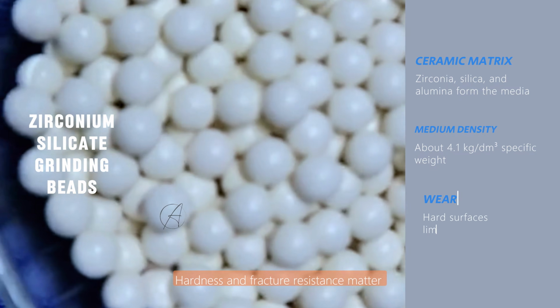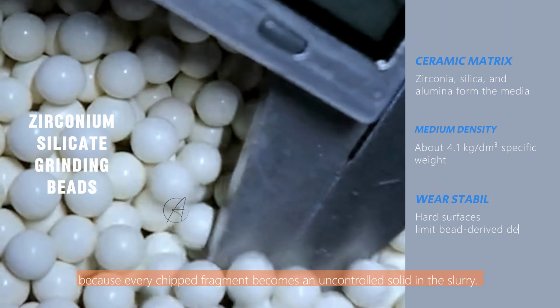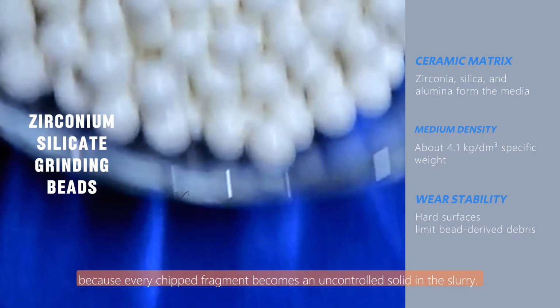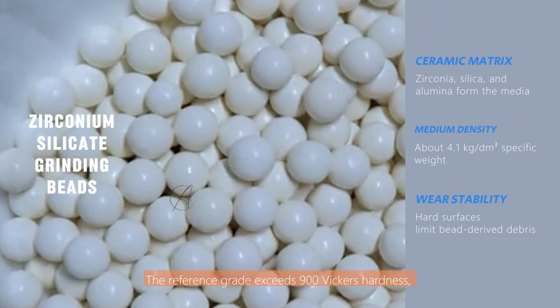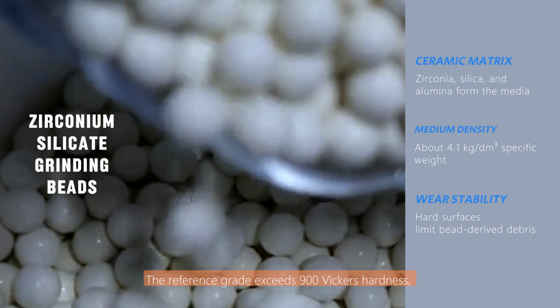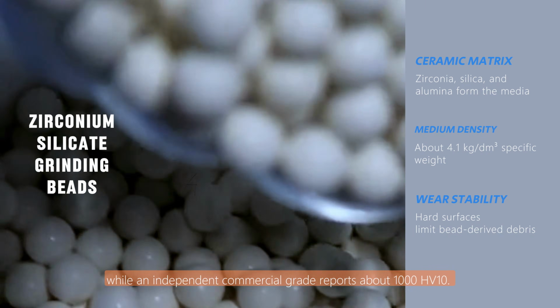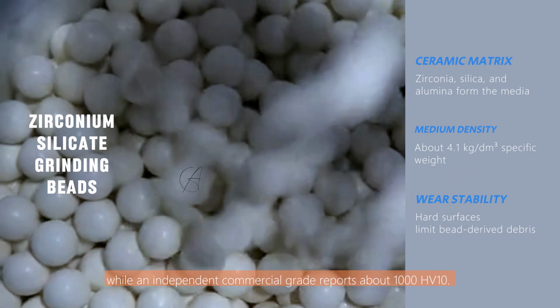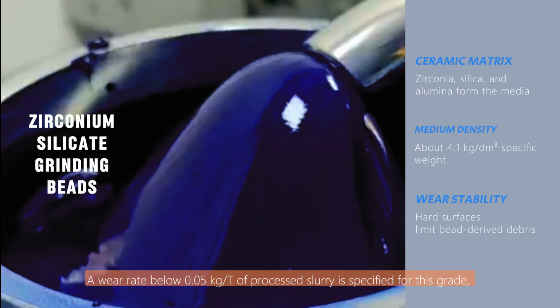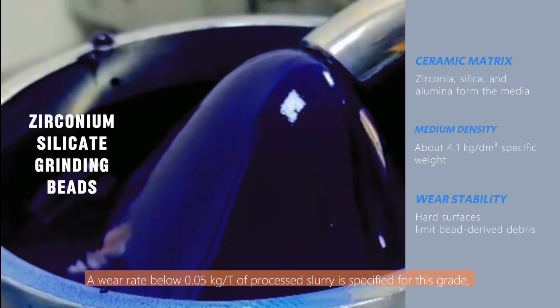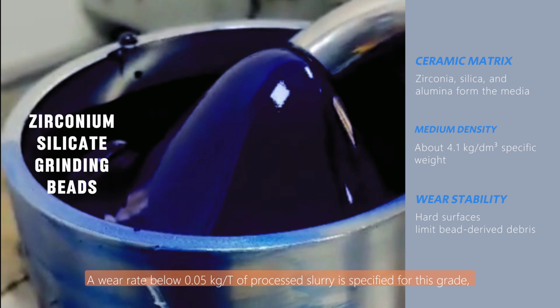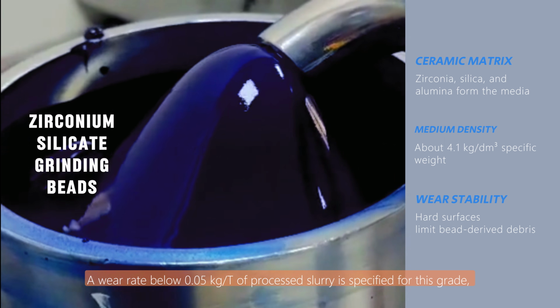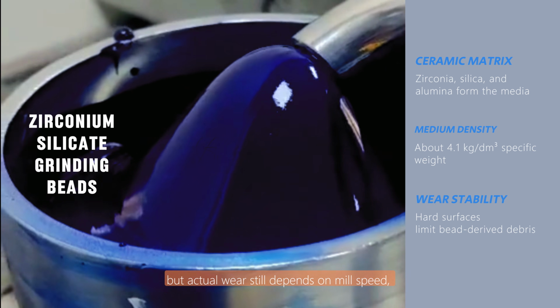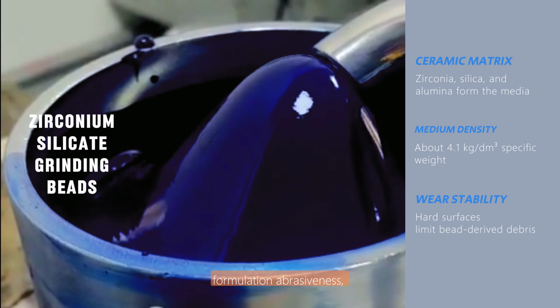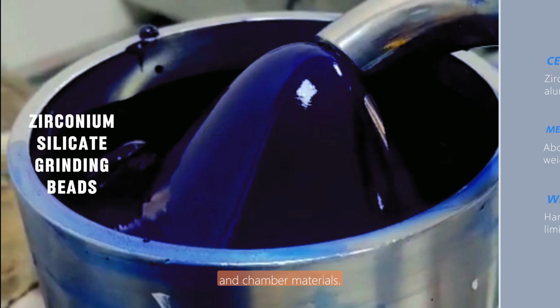Hardness and fracture resistance matter because every chipped fragment becomes an uncontrolled solid in the slurry. The reference grade exceeds 900 Vickers hardness, while an independent commercial grade reports about 1000 HV10. A wear rate below 0.05 kilograms per ton of processed slurry is specified for this grade, but actual wear still depends on mill speed, formulation abrasiveness, and chamber materials.